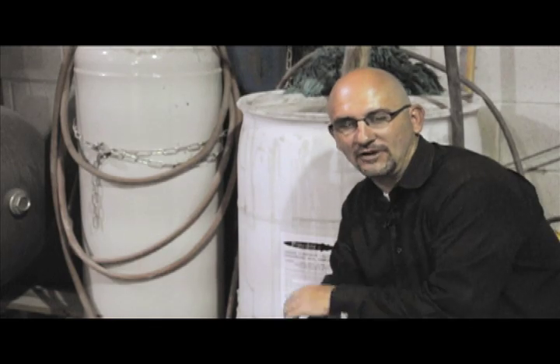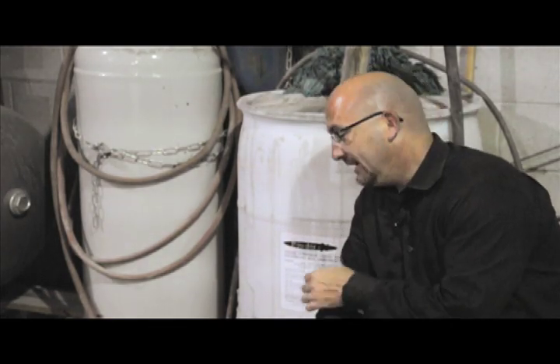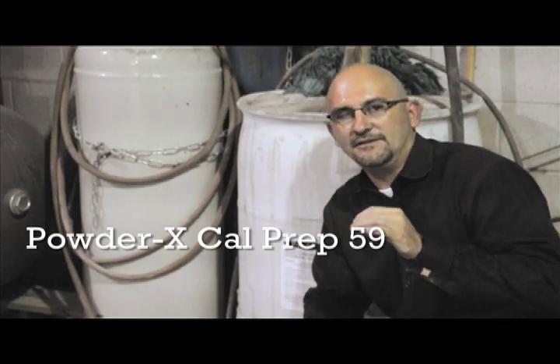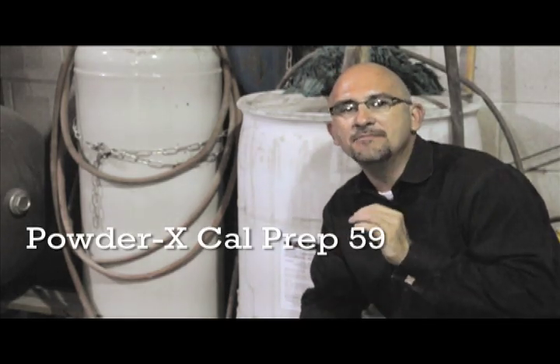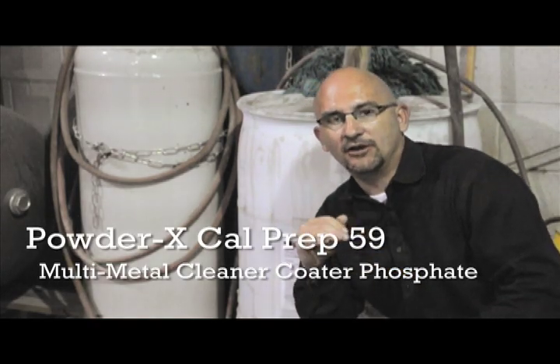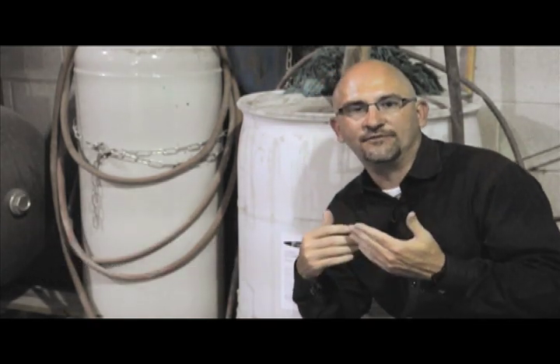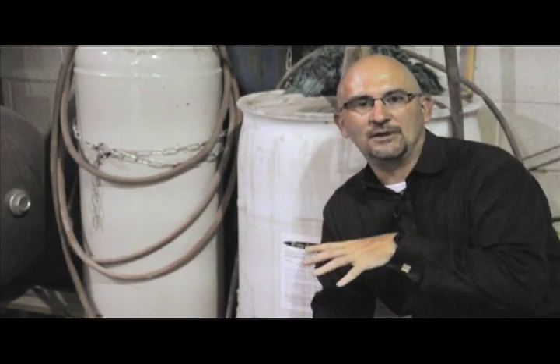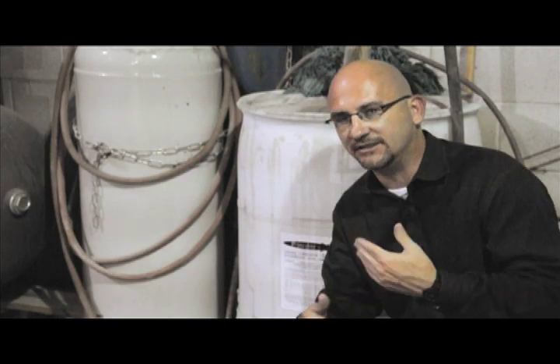Okay, Matt, the chemical that we use in the videos is CalPrep 59 by Powder X Coating Systems. It's a very specifically formulated multi-metal cleaner coater phosphate. The reason we specify multi-metal cleaner coater versus just saying give me a phosphate is simple. Cleaner coater tells the chemical supplier they're going to provide you with a phosphate that has surfactants or soaps in it. So while it phosphates your product, it'll also act as a degreaser and a cleaner.